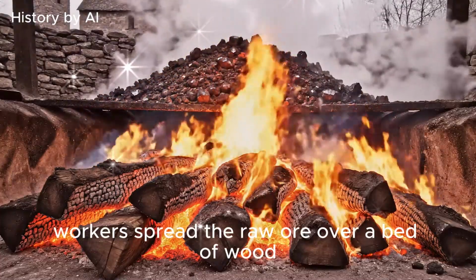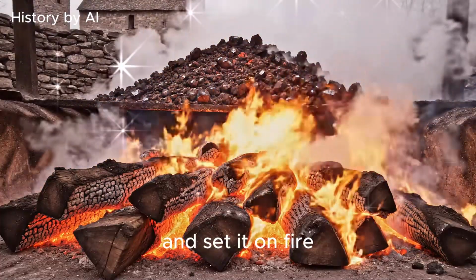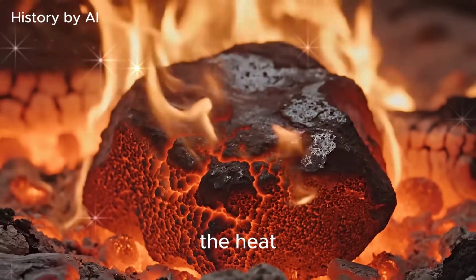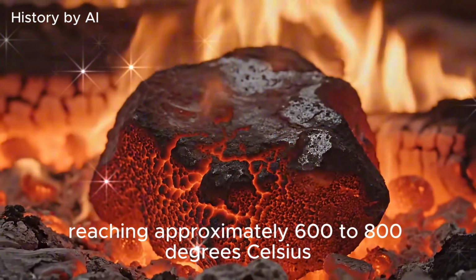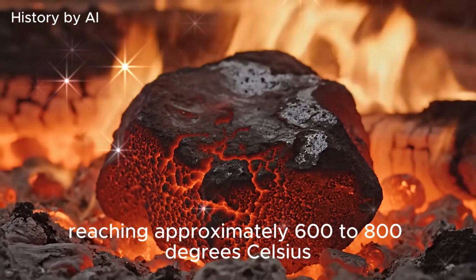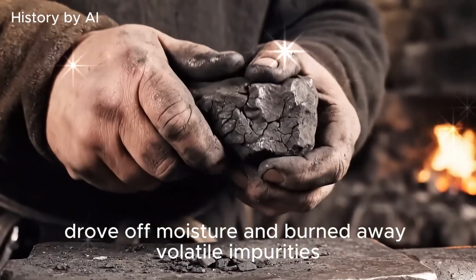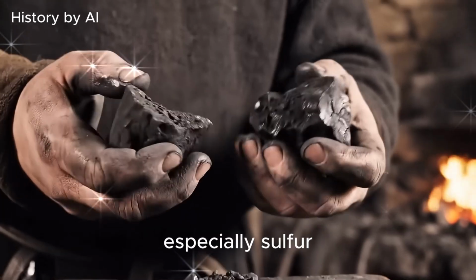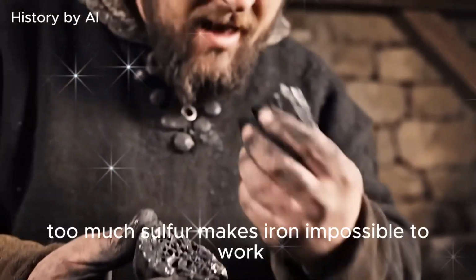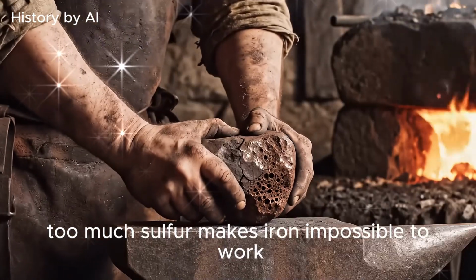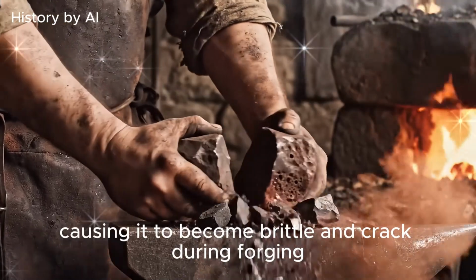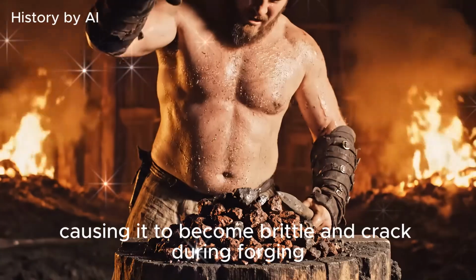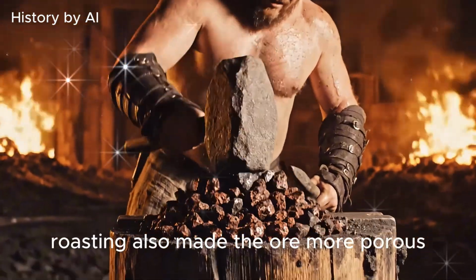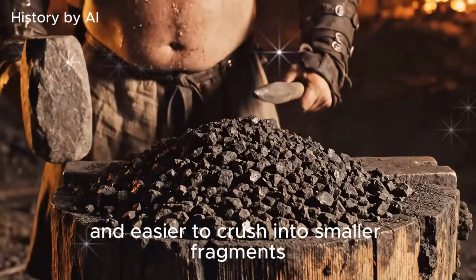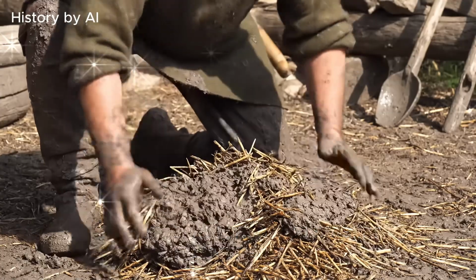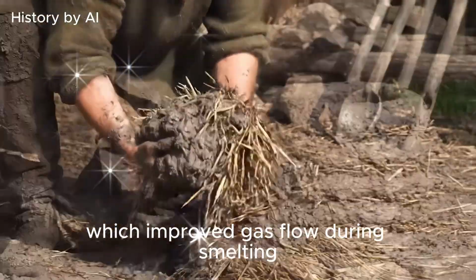Workers spread the raw ore over a bed of wood and set it on fire. The heat, reaching approximately 600 to 800 degrees Celsius, drove off moisture and burned away volatile impurities, especially sulfur. Too much sulfur makes iron impossible to work, causing it to become brittle and crack during forging. Roasting also made the ore more porous and easier to crush into smaller fragments, which improved gas flow during smelting.